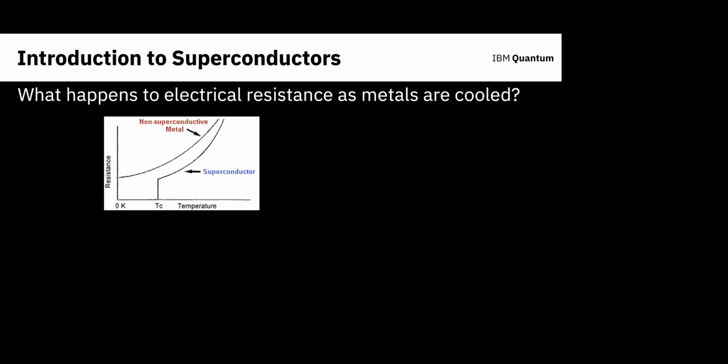and he found superconductivity. If you remember your condensed matter physics or your thermodynamics, you might remember that the resistance of a material goes down as the electron-electron collisions go down and the phonon modes go down. But you expect it to retain some residual resistance even at 0 Kelvin. Now, for a superconductor, what happens is that resistance continues down, but you reach some point called the critical temperature, or TC, at which it completely drops to 0. So these metals lose all electrical resistance. And that is kind of a weird thing.